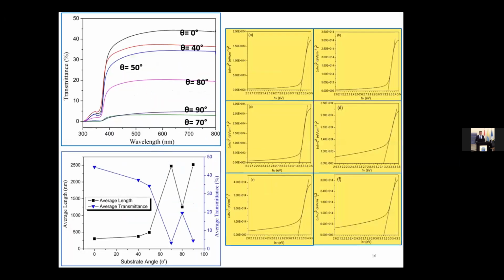Also, the optical properties of zinc oxide nanorods for different inclined angles have been studied by optical transmittance spectroscopy. We can see from this figure the substrate inclined angle changes the optical properties of the zinc oxide nanorods. Also, the energy band gap ranges from 3.2 to 3.16 eV.